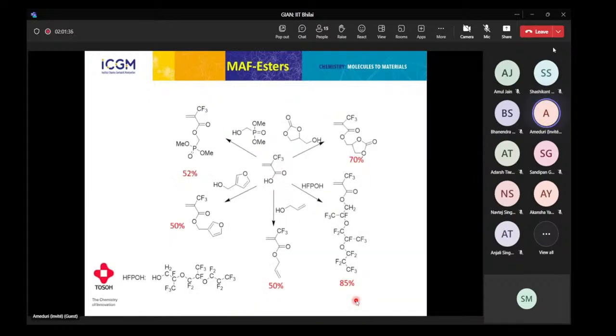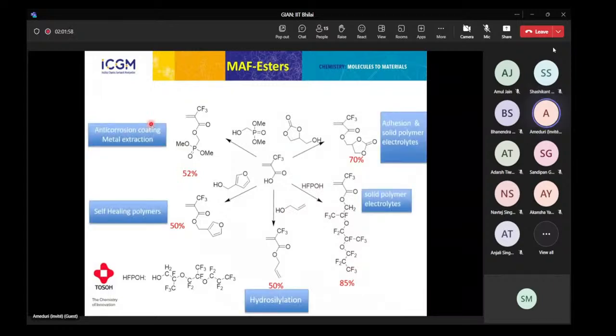So we decided to work and to modify this MAF. So Sanjeev, you have some memories, and to put some phosphonate, some furan, some cyclocarbonate, some allyl compound, or some fluorinated ether, because behind that there was an idea for anti-corrosion coating, because phosphorus is very important, especially phosphonic acid, which can adhere on steel and enable some anti-corrosion, and also metal extraction.